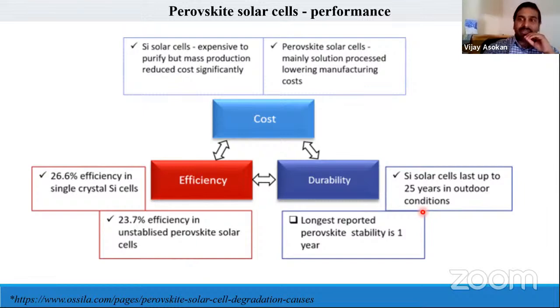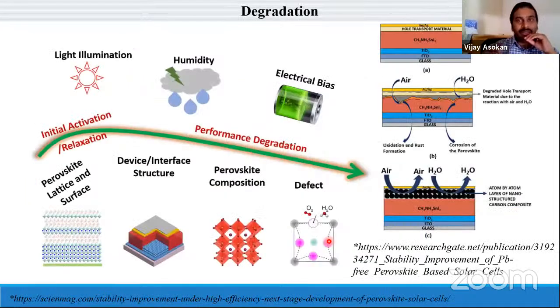Considering the durability factor, silicon solar cells last up to 25 years in outdoor conditions. But the only problem with perovskite solar cells is that the longest reported stability so far is around 1 year. That's the only thing we need to consider now. Irrespective of the other advantages of perovskite, this needs to be concentrated on further in research to improve the stability.